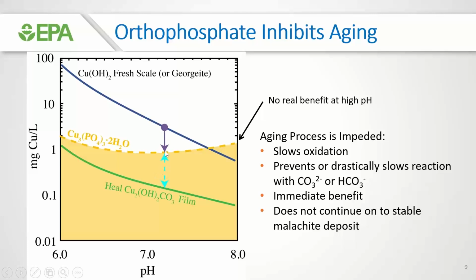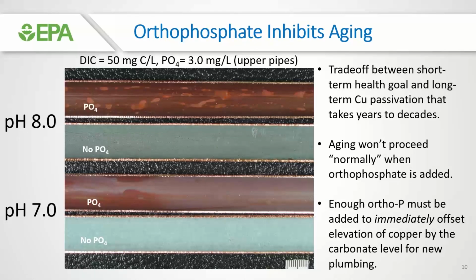Now, the downside to this is that you will observe an immediate benefit, but you won't fully benefit from that full aging process. So it sort of stops. Aging sort of stops with the addition of the orthophosphate. So what you see is an initial, potentially big benefit when it comes to getting down below the action level. However, ultimately in the long run, you might not see the benefit of fully achieving the stable, ideal cupric oxide or malachite scale that could form as the aging process goes on.